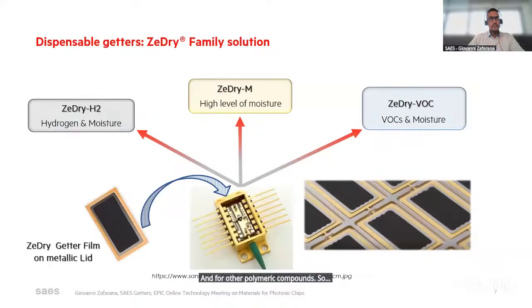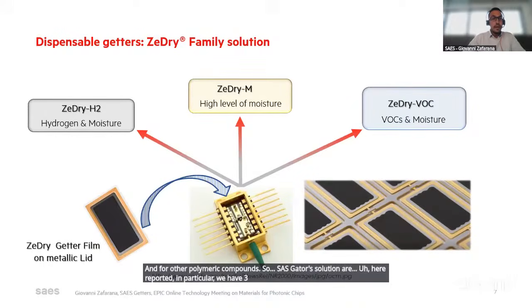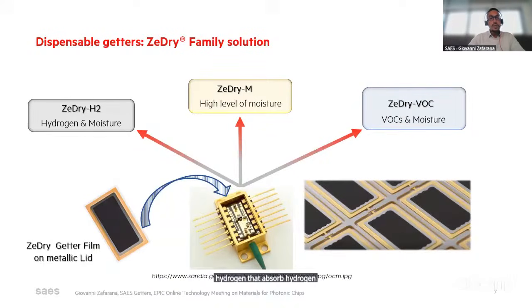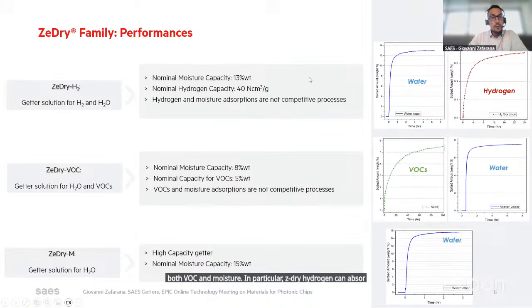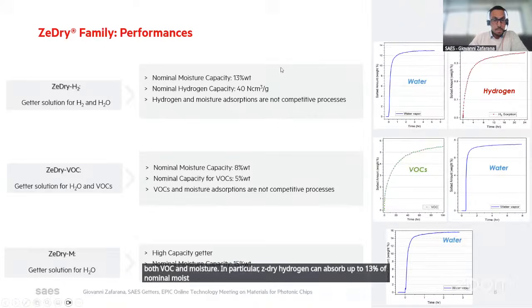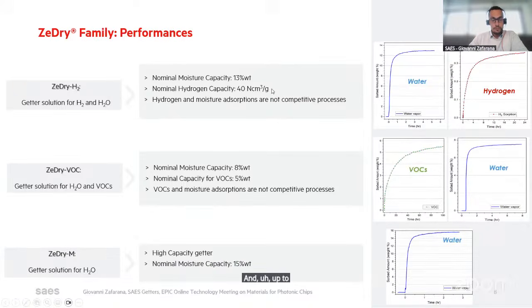So SAES Getters' solutions are reported here. In particular, we have three products: Z-Dry Hydrogen, which absorbs hydrogen and moisture; Z-Dry-M, which absorbs a very high level of moisture; and Z-Dry VOC, which absorbs both VOC and moisture. In particular, Z-Dry Hydrogen can absorb up to 13% of nominal moisture capacity and up to 40 cubic centimeters per gram of nominal hydrogen, and the hydrogen and moisture absorption are not competitive. Z-Dry VOC can absorb 8% of moisture and 5% of VOC, and Z-Dry-M can absorb up to 15% of water.